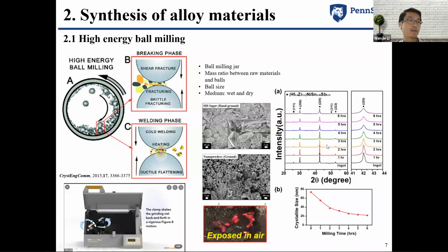So this is one example of the half-Heusler materials we prepared in our lab. This figure shows the hand-ground powders from the ingot, and this is the ball-milled powder. We can see the particle size is much smaller and uniform, obtained from the high-energy ball milling. And this is an example of how fine the particles are.